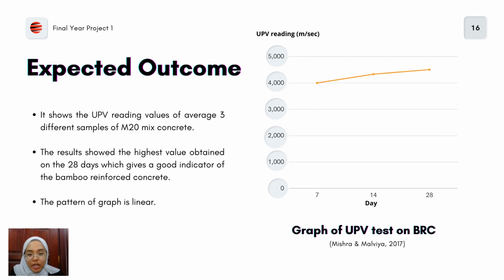For the fourth expected outcome, I focus on the graph of the UPV test on BRC, which was conducted by Mishra and Malviya in the year 2017. As observed, it shows the UPV reading value averaged over 3 different samples of M20 mixed concrete. The results show the highest value obtained at 28 days, which gives a good indicator of the bamboo reinforced concrete. And this graph shows a linear pattern.